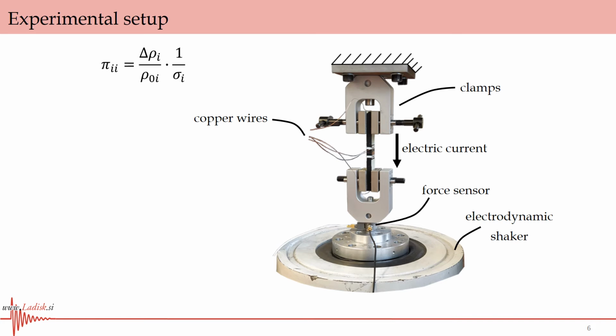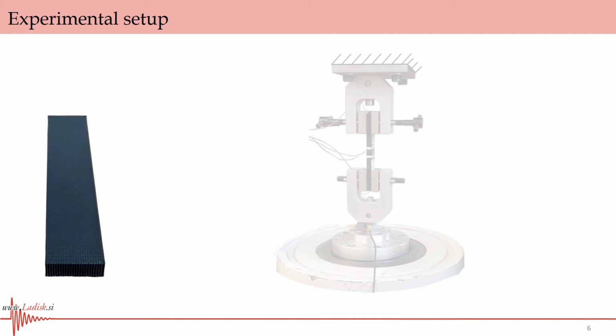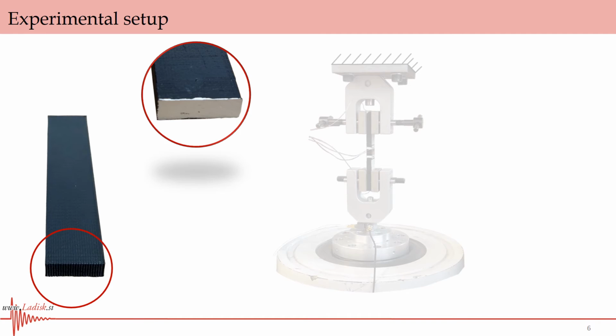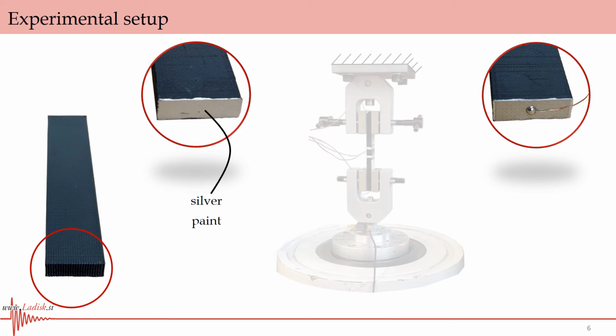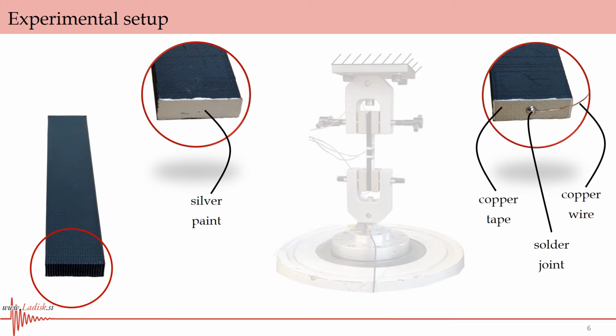Additionally, force and acceleration were measured. To obtain reliable results, good electrical contacts have to be achieved. At first, surface was painted with a highly conductive silver paint, and afterwards, copper wires were soldered to the conductive copper tape, which was then taped to the painted surface.